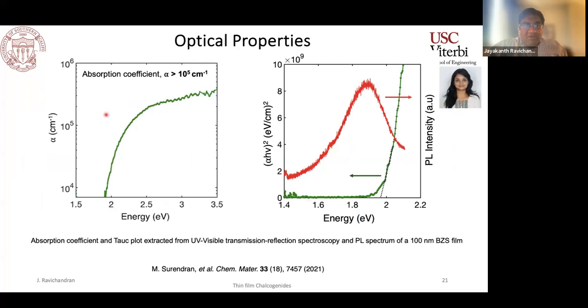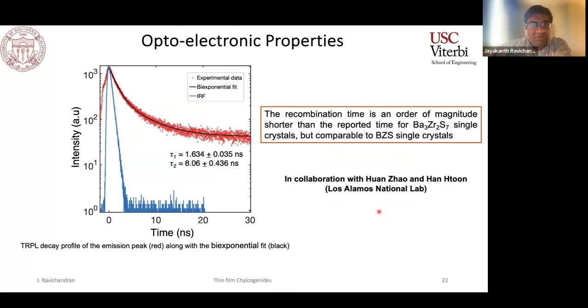So we also studied its optical properties. It turns out we could measure very reliably the absorption coefficient once we started growing them in thin film form. It was much harder to do in crystals, or nearly impossible given the geometry of the crystals we were getting. And we also saw luminescence, very muted and very similar to what we saw in our single crystals, presumably something intrinsic to BaZrS3, which is something we have studied on other occasions. We also compared the energy at which your luminescence happens to the absorption edge, and they seem to match reasonably well with the literature, within the error bar of the energy ranges that people have reported.